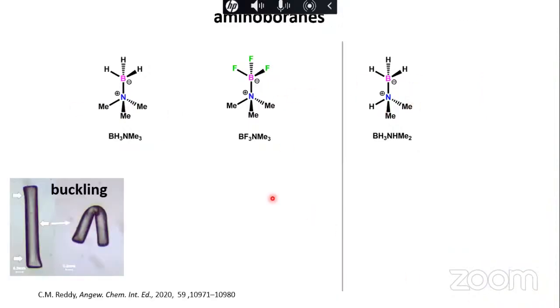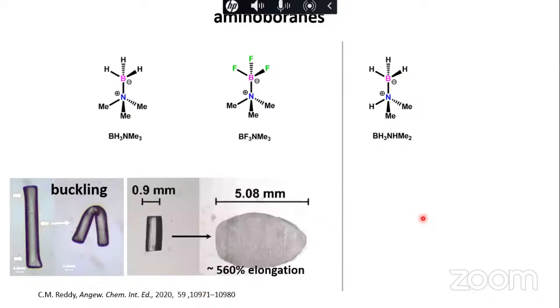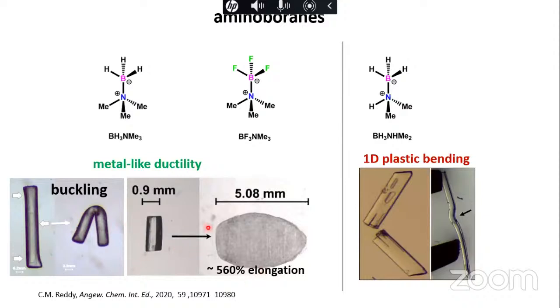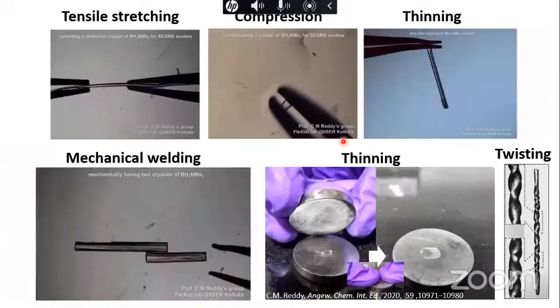So although they look very similar, there are large differences in terms of the properties. These 2 crystals have dynamic disorder. So these are very, very soft, and they show very good plasticity. For example, if you take these crystals and press them, you can see that they spread and become like a thin film. But in this case, it bends on one of the faces. If you try to bend them in other phases or try to do anything, these crystals simply break, because this does not have the dynamic disorder. The molecules don't rotate, because they have strong hydrogen bonding, dihydrogen bonding interactions. But in the other cases, they don't have strong hydrogen bonding interactions. Because of that, the molecules start rotating in the solid state.